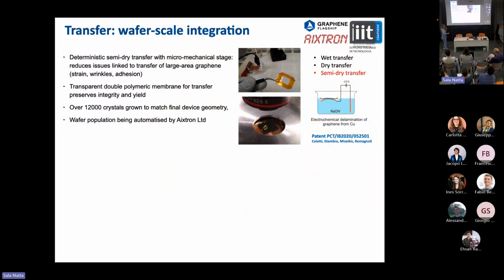That means that you are able to laminate your graphene without making it dirty, because when you transfer, inevitably your graphene gets contaminated. If you do it wet, you will get some molecules of water, atoms of some sodium, if you use sodium. And of course, that is going to diminish the purity of the material a bit. So we had to find and develop a way to do it as clean as possible, with patents on different approaches.